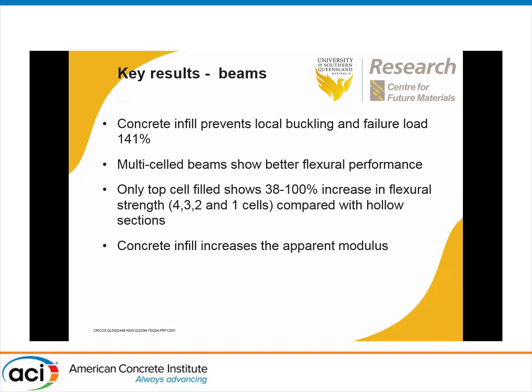Then we can see there are some key results. Concrete infill can prevent local buckling, and the failure load can be increased by about 1.4 times, 40% extra. Multi-cell beams show much better flexural performance, and by only filling the top cell rather than filling the whole multiple cells, we can improve the characteristics in a much better way, because we are filling the compressive side. And of course the concrete infilled tubes increase the apparent modulus as well, basically increasing the stiffness of the product.